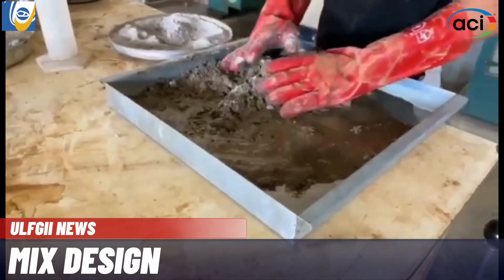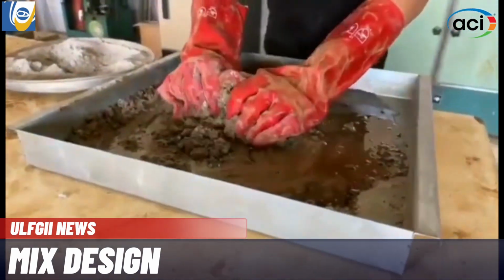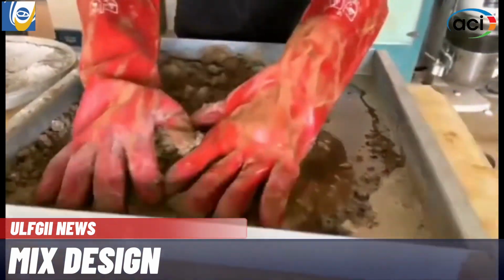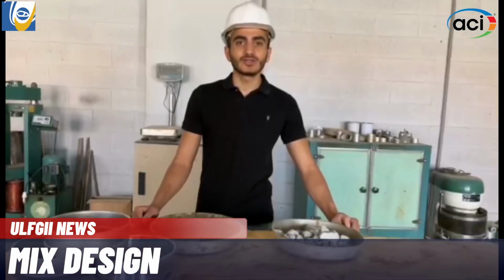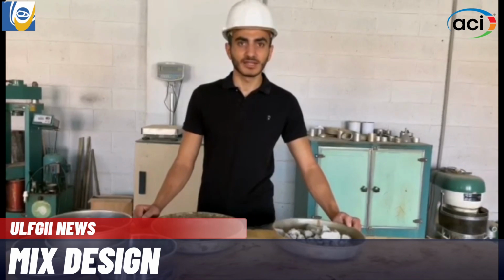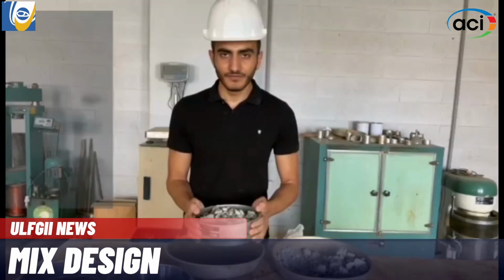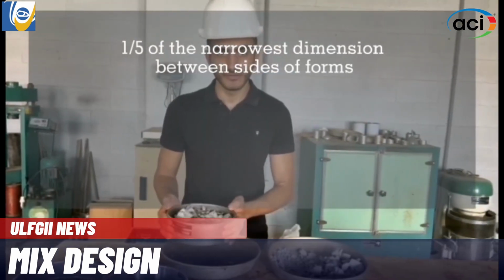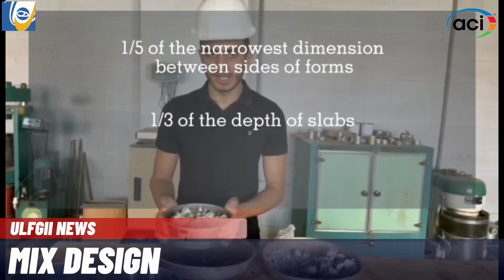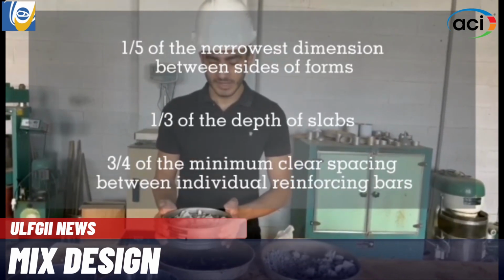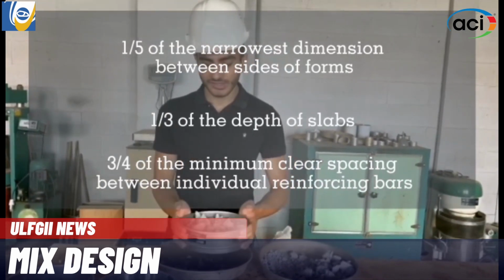Several tests and experiments were made to find the best mix design. The results obtained have shown that the ACI mix design gives the best strength for the recycled concrete aggregate. The mixing method consists of several steps. First of all, we start by choosing the maximum size of recycled aggregate, according to three conditions that the maximum recycled aggregate should not pass. First, 1/5 of the narrowest dimension between sides of forms. Second, 1/3 of the depth of slab. Third, 3/4 of the minimum clear spacing between individual reinforcing bars.